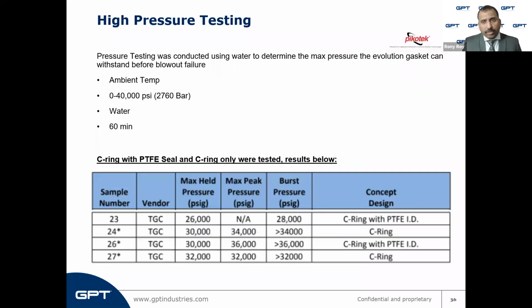We have also tested evolution in high pressure tests. In this example, we tested in ambient temperature for 60 minutes of hydro testing. The worst performance we had seen was 28,000 psi when we tested 4 samples, and that also was not because the evolution had leaked, but the flanges were lifting off. Even the 32,000 psi and 36,000 psi are all leakages when flanges started lifting off at such high pressures.